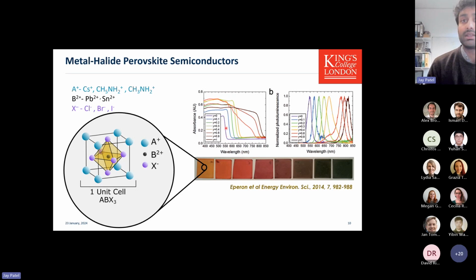You can see when there is very little iodine but lots of bromine, you start to absorb only blue light. But if you add a lot of iodine and not a lot of bromine, which has a smaller atomic size, then you start to absorb a lot of the red and the infrared light. And so this property of metal halide perovskites is incredible. It now allows us to create this tunable material that can absorb different colors of light, and therefore you'll be one step closer to attaining a higher efficiency solar panel.